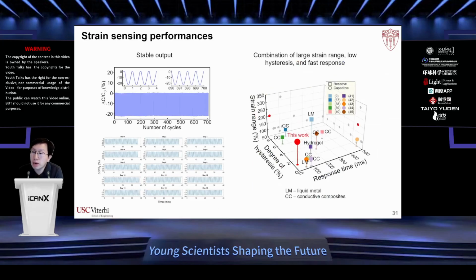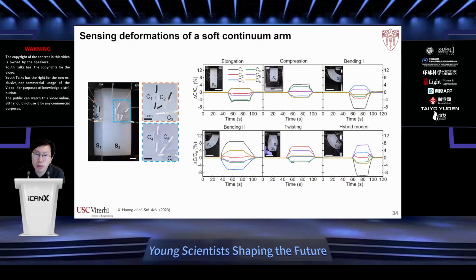And if we compare the three most important characteristics of strain sensor that we care about, which is the strain range, degree of hysteresis, and the response time, this origami-inspired strain sensor has a pretty good combination of these three. And we can arrange them in different configurations to measure soft material deformation. In this example is a passive soft arm. We can detect its deformation mode based on the strain sensor signals.